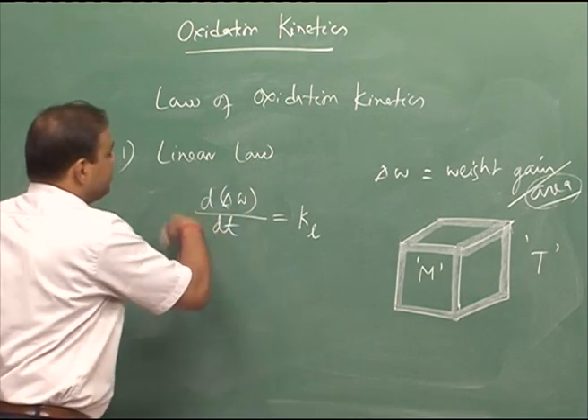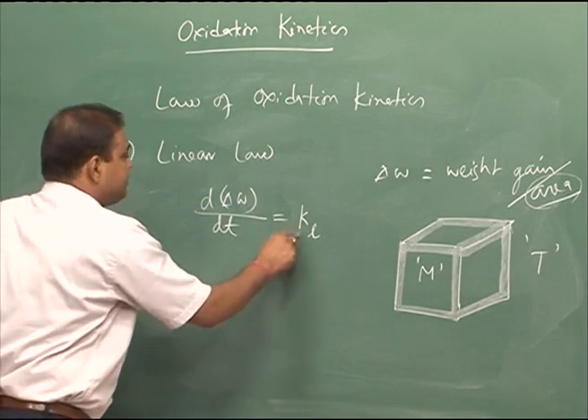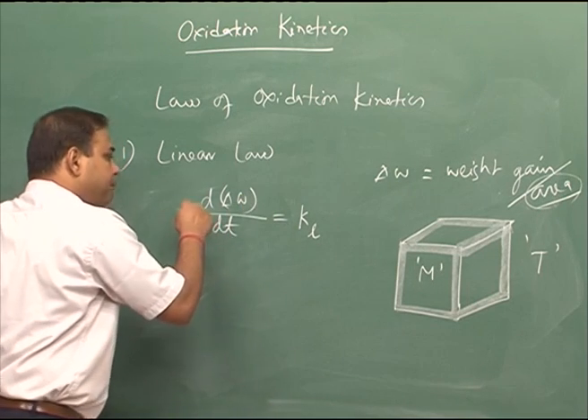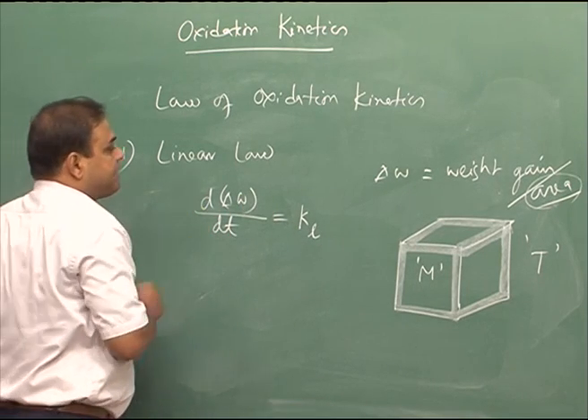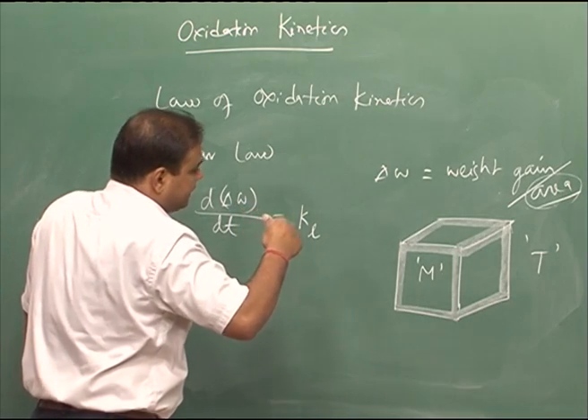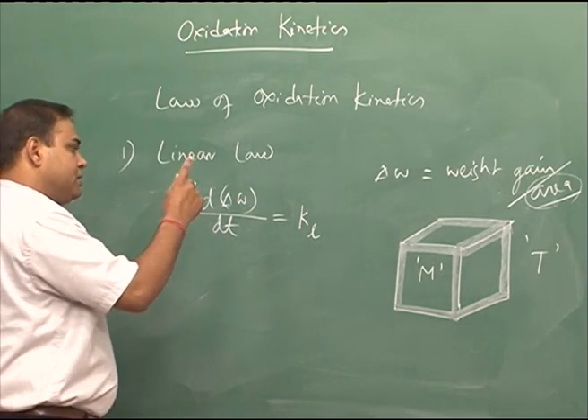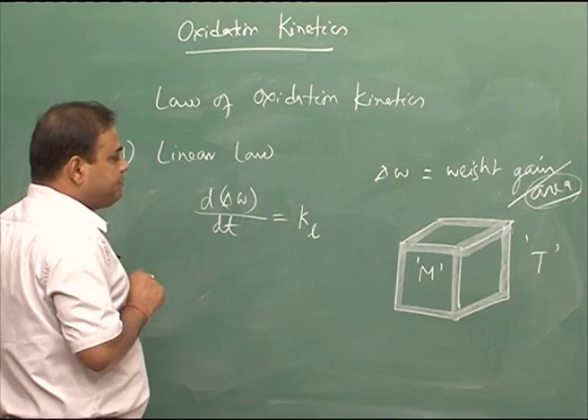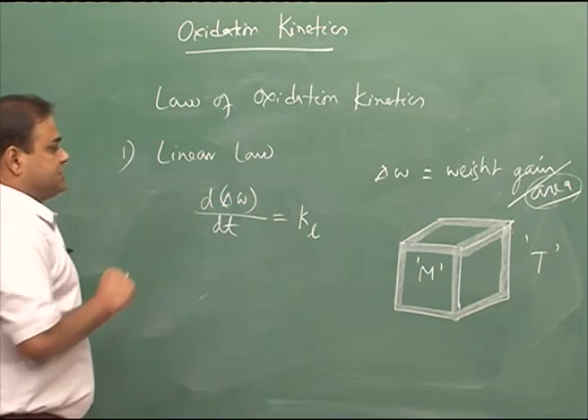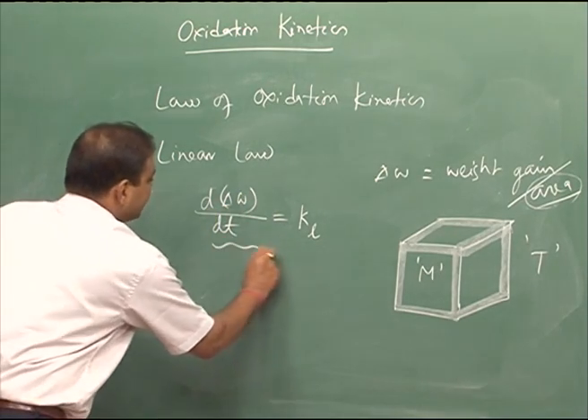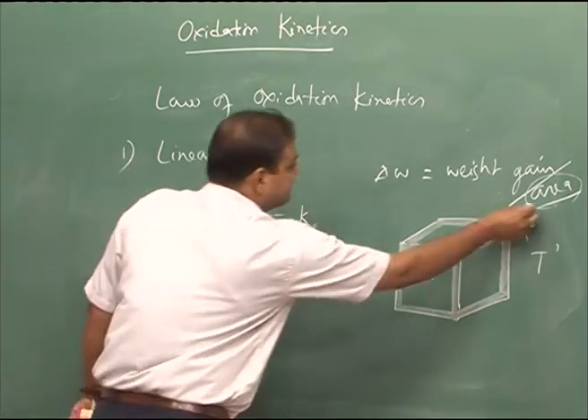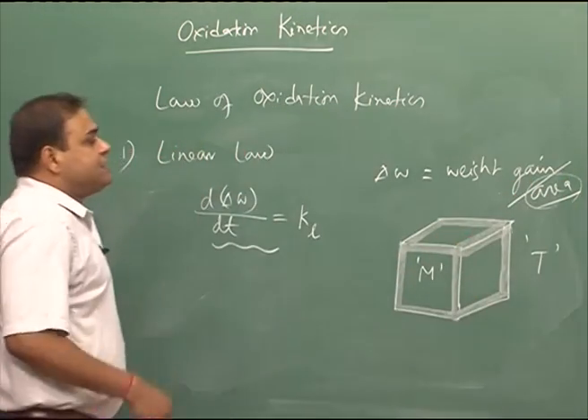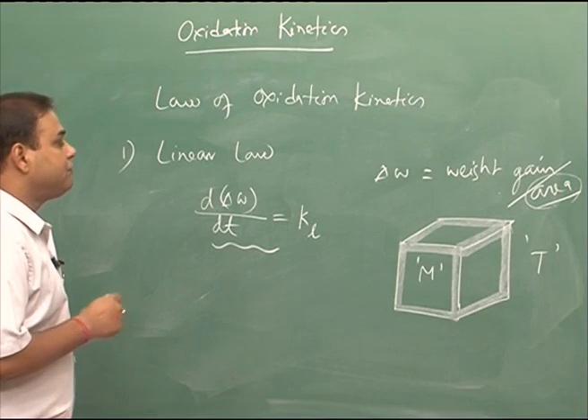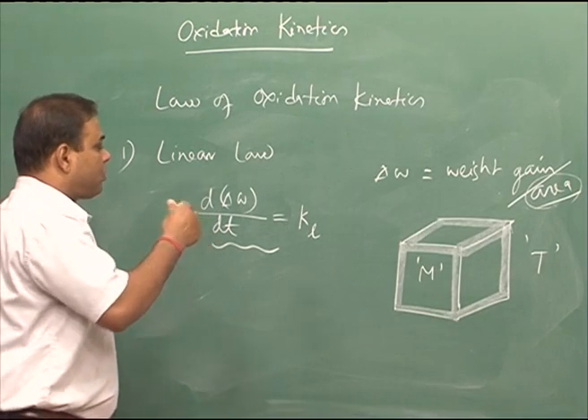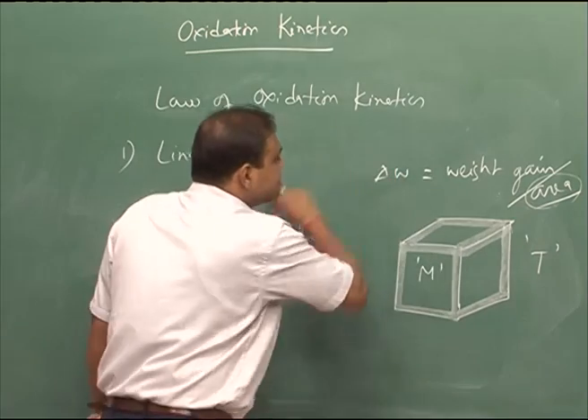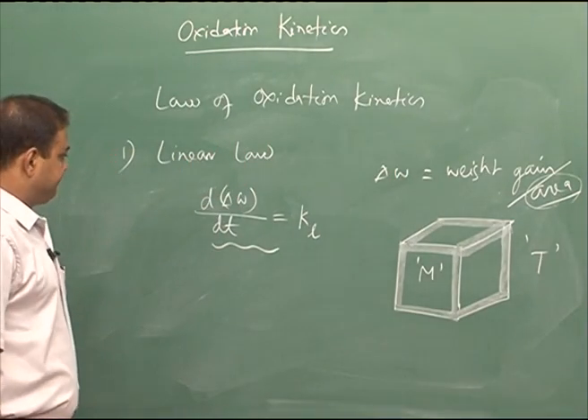The change in weight per unit time would be the same, even if you start from t equal to 1 minute or t equal to 10 minutes. So, that is the linear law, and we see that if we divide by area, that would give you the actual picture of the oxidation process, or the rate at which oxide is growing.